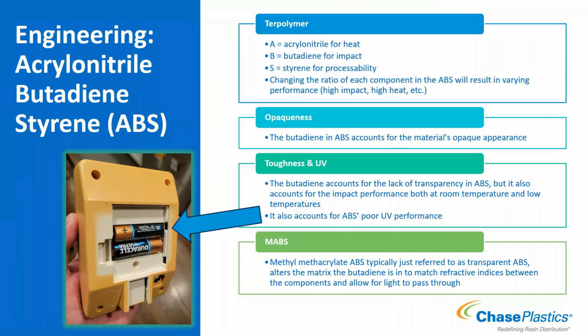So what we can do is we can change the ratio of how much of each of those components is in the ABS grade, and that's what allows us to get varying performance out of ABS. So if you look at some data sheets on a standard general purpose ABS, maybe you're looking at an impact value of a 4, 5, 6 foot-pounds per inch IZOD. Then you have grades that are considered high impact grades that get you into the 8 or 9 foot-pounds per inch notched IZOD performance. And then you have high heat ABS grades.